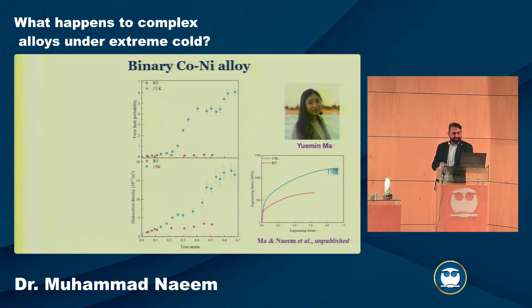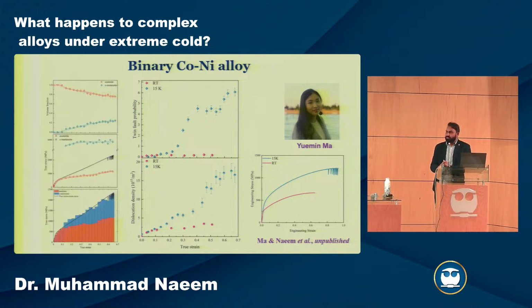And in this case, again, we quantified different mechanisms, and at low temperature, the dislocation density becomes significantly higher. We have a very high twin fault probability, but there is also martensitic phase transformation happening in this case, which is contributing to a very high strain hardening rate. These mechanisms come together to give rise to higher ductility as well.